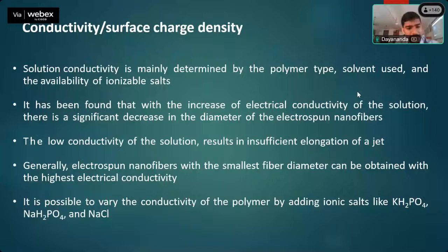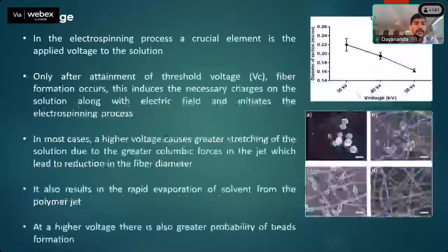Whatever nanofiber diameter we get will be very less. The conductivity of the polymer solution can be tuned or modulated. If it is not conducting, we can add certain ionic salts to modify the conductivity. Such as sodium chloride salts can be used to increase the conductivity of the polymer solution. And coming to voltage, that's an important parameter too.